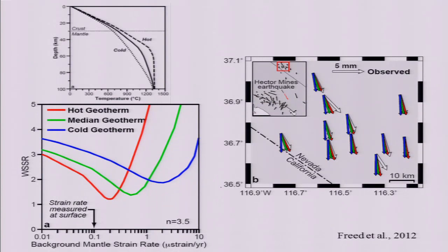Next point. All right, a next scale observation, and this gets to Gigi's other question. So the short answer to your question, Gigi, is that in the laboratory, we make diffusion creep happen really fast by making the grain size teeny. Remember that the diffusion creep flow law depends on 1 over the cube of the grain size. So by making these powders with a 1 micron grain size, rather than a 1 millimeter grain size, we enhance diffusion creep by 9 orders of magnitude, approximately. In the Earth, the grain size isn't 1 micron. And so in that plot I showed you, with a grain size of 1 millimeter to 10 millimeters, the transition stress is more like 1 MPa to 10 to the minus 3 MPa.